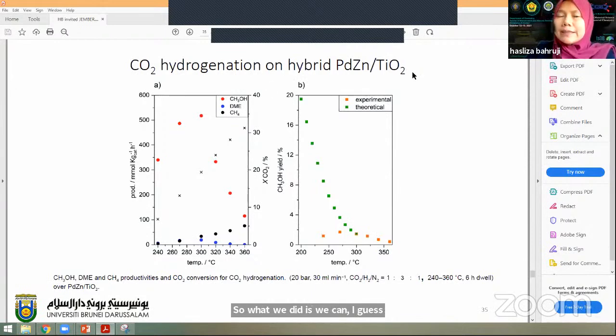This is on palladium zinc titania only. And then when we increase the reaction temperature up to 360, we start to see, the red one over here is the methanol production. At low temperature, methanol actually is favored. Then up to 300, it starts to drop to give more methane formation and some DME production. So more methane, and this one is the conversion. The conversion always increases with the reaction temperature, it's just that the selectivity will be reduced.